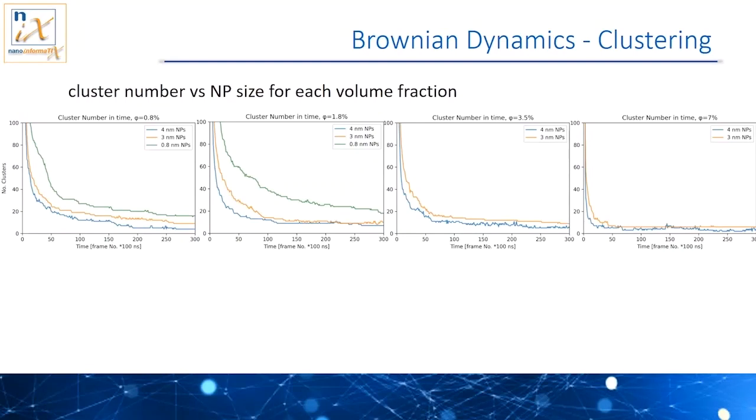So, to summarize, we employed classical molecular dynamics simulations with the umbrella sampling technique to get the free energy profile for the aggregation of 2 identical nanoparticles in explicit water. We fitted the repulsive short range and the attractive long range parts of the curve, and we built a table potential we then used for running Brownian Dynamics for at least 30 microseconds of trajectory.